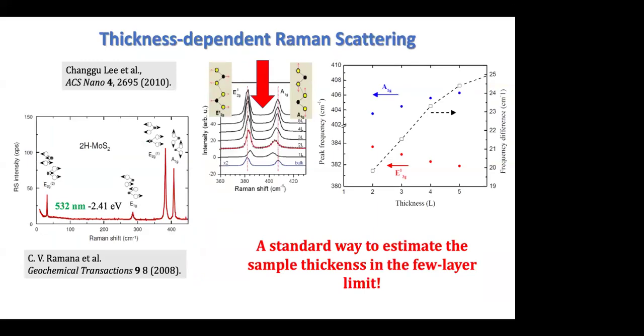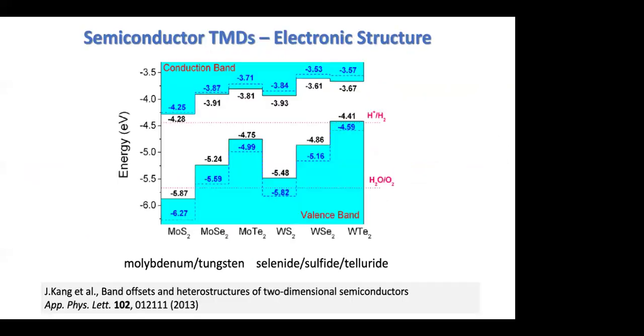And finally, Raman scattering can also give you some information about the thickness of your structure, because, as in the case of molybdenum disulfide, the energy difference between the fundamental vibrations, in-plane E2g and out-of-plane A1g, strongly depends on the thickness of your sample. So looking at the Raman spectrum, you can judge how thick your sample is, and this works to a higher or lower extent also in other materials. So this is the way you can find the thickness of your material.